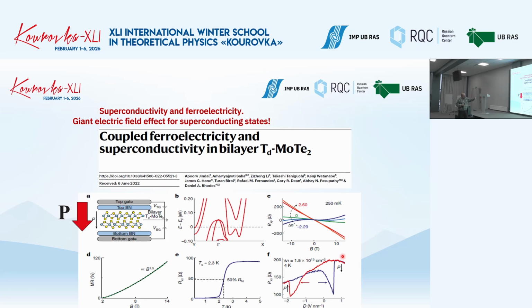But basically, it's very similar, and we see experimentally, not we, but they see that resistance switches from zero to non-zero. And it looks like, look at this picture, for large dipole moments which point in the same direction, you have some finite resistance. It's a resistive state. If you change the orientation of the dipole moment to the left, you again have some finite resistance, no superconductivity. But in between, when we are supposed to have some domain structure of sliding ferroelectric domains.